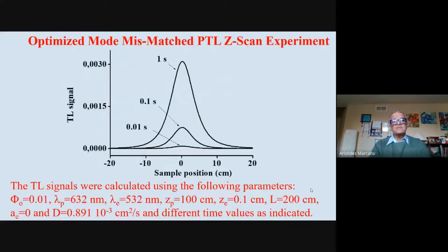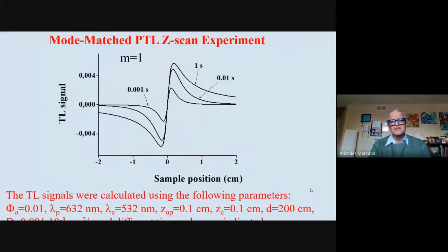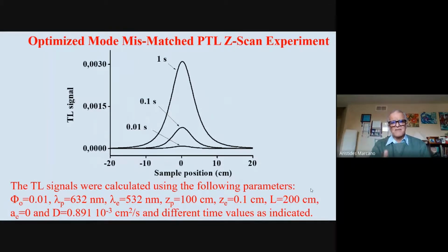But if you do the mode mismatch, the method we use, you get this kind of shape, which is only one single beam. It means that at the center, what you see in the typical Z-scan, when you have the maximal intensity, you have a very small signal. But here, at the center, you have a maximal signal right there. It's more or less easy to understand. You should have maximal signal when you have the biggest intensity, and that is one of the reasons I recommend it. The interpretation of the experiments is easier when you do the mode mismatch experiment.